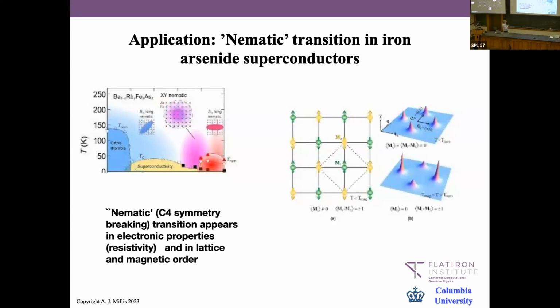Ian settled a controversy related to some of the iron arsenide superconductors, which exhibit a phase transition from a high temperature state where the crystalline symmetry is square to a low temperature state where the crystalline symmetry is rectangular. So you break C4 down to C2, right? And there was controversy for a number of years about whether this transition was driven by electronic or lattice effects.